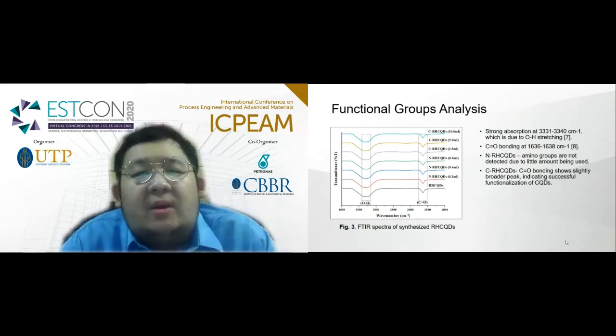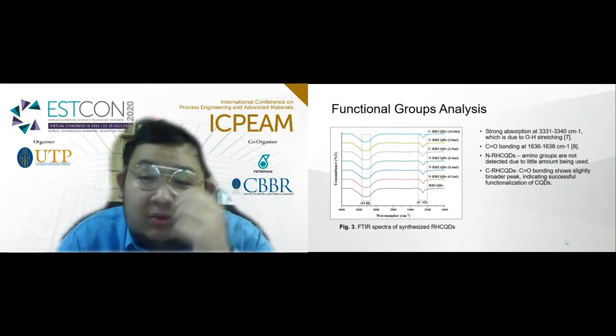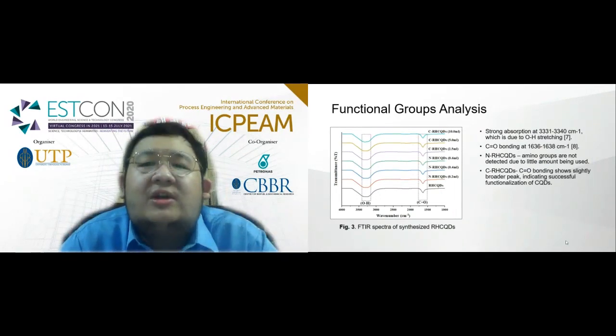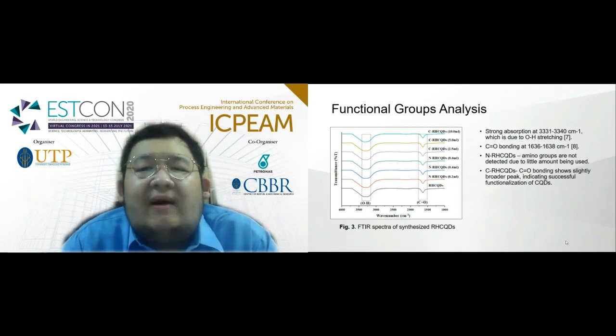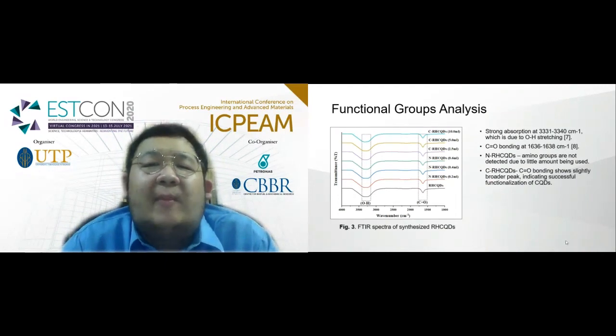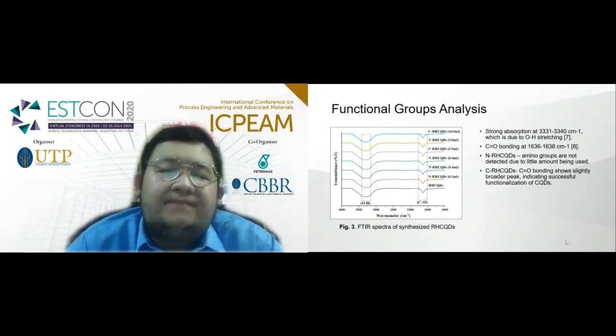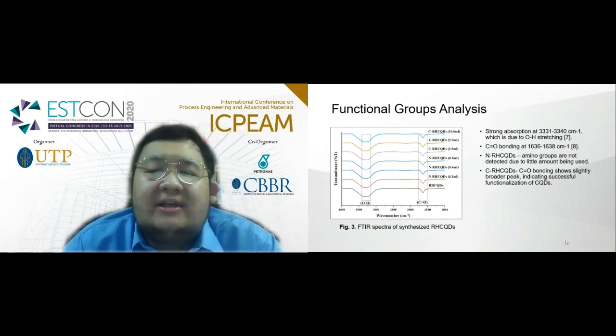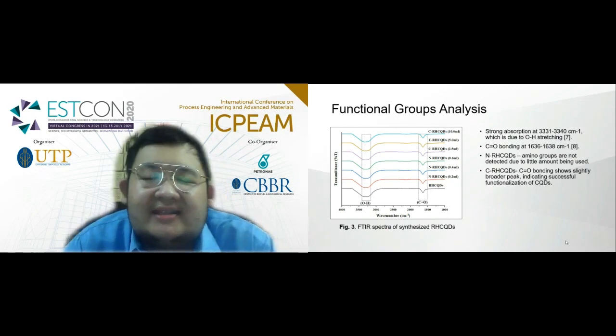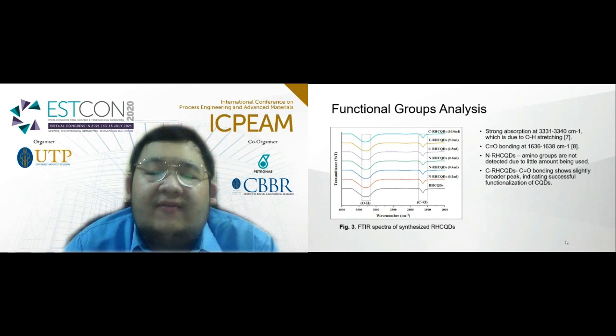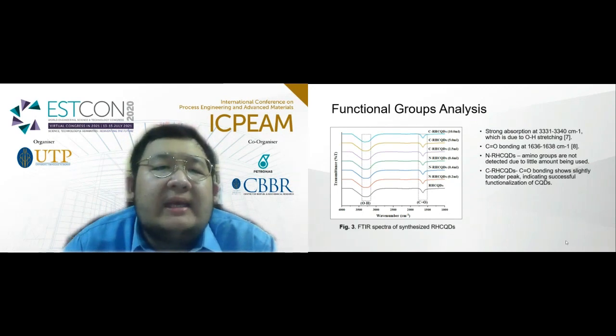Functional groups of carbon quantum dots are tested using FTIR. Strong absorption at 3,331 to 3,340 is due to O-H stretching. C=O bonding is found at 1,636 to 1,638. This indicates the successful formation of carbon quantum dots. In the case of amino CQD, the amino group is not detected due to the little amount being used. For carboxyl CQD, the C=O bonding shows a higher, slightly broader peak. This indicates the successful functionalization of the carboxyl group onto the surface of CQD.